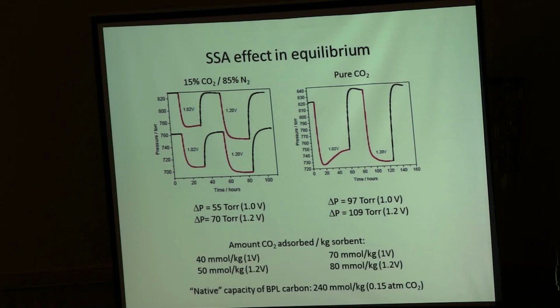We can also ask the question: what is the effect when you use pure CO2? We found that then the pressure changes are increased. However, they are disproportionately smaller than what you would expect, because you increase the CO2 partial pressure by about a factor of 6. However, you see that the pressure changes increase only by a factor of 2. This means that the technique is relatively insensitive to the partial pressure of the CO2 in the gas mixture.